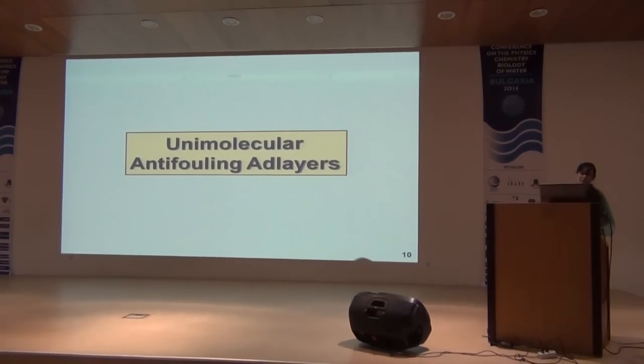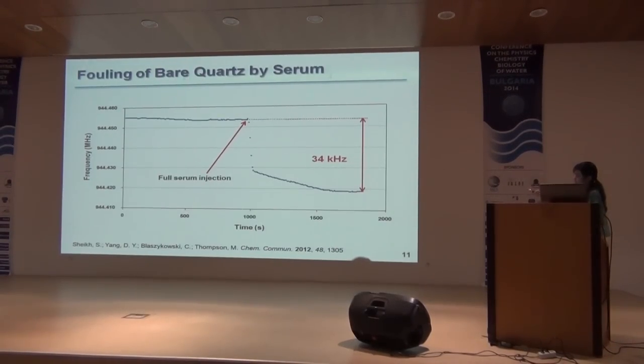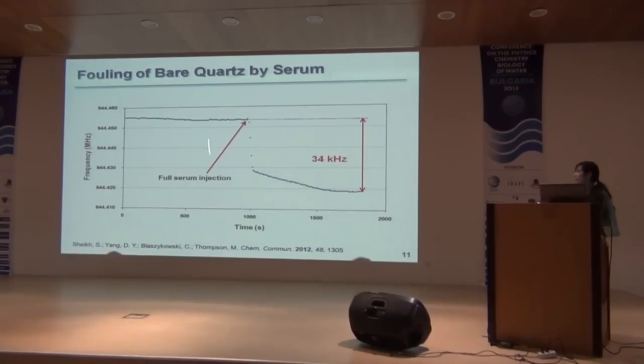At this conference I presented my work on unimolecular antifouling ad layers — using one type of surface modifier on the surfaces to evaluate antifouling behavior when exposed to serum samples. Before getting into the surface modifier results, let's look at how bare quartz behaves when exposed to serum. Once we inject full serum, we see a huge frequency shift of about 34,000 Hz, so we can conclude that bare quartz is very prone to fouling.